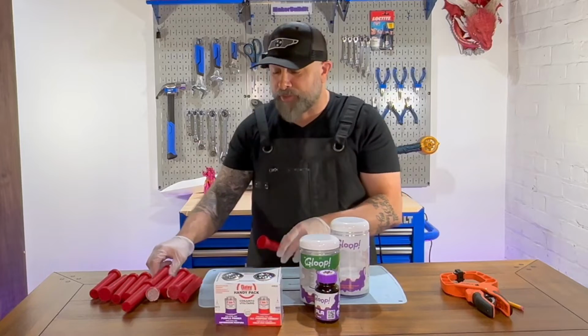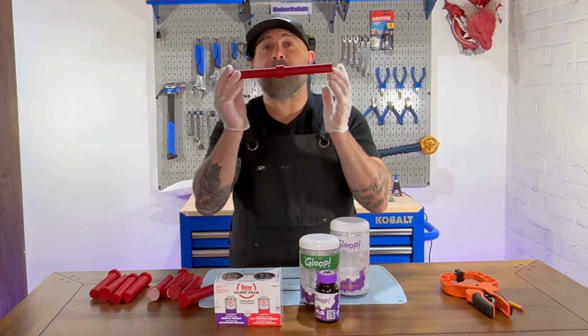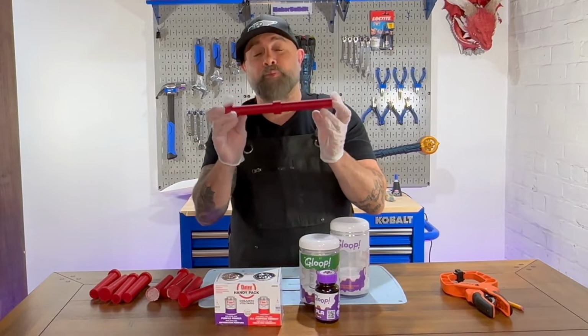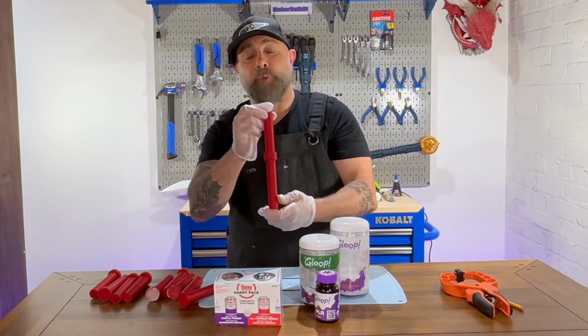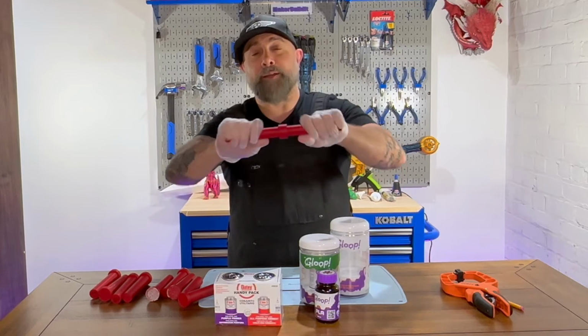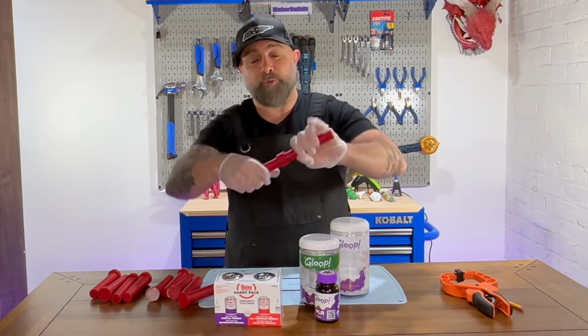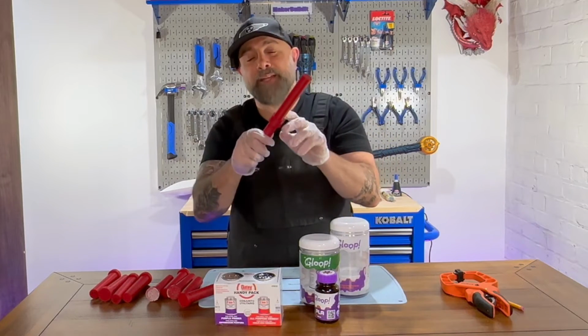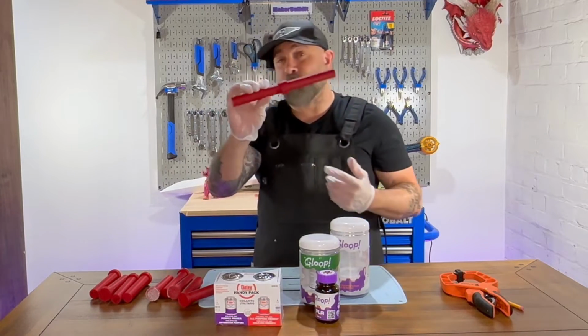We're going to take this, which was from our test of different types of 3D printing glue. This was our 3D Gloop one. And we could not break the bond. It actually broke by twisting apart. We were able to snap it, but it didn't break the bond. It actually broke the PLA.